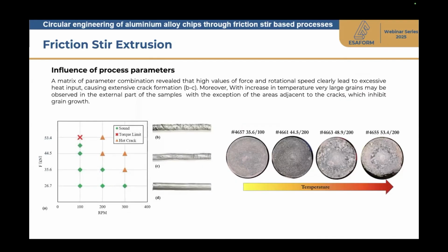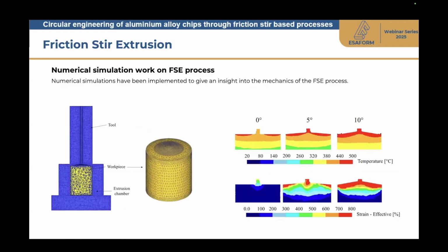Here you can see a process map for this operation, namely at the varying of tool rotating speed and extrusion force, we obtain some different conditions: a sound product, a torque limit of the machine, or hot cracks. Namely, we can't go too high with values of tool rotating speed and extrusion force, since otherwise we obtain too large levels of temperature, and in this case we obtain a product characterized by extensive cracks on the surface, as shown in this figure. And of course, also the average grain size is different at the varying of the temperature distribution in the wire during the process.